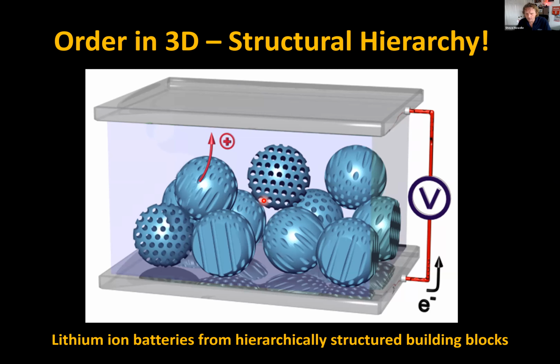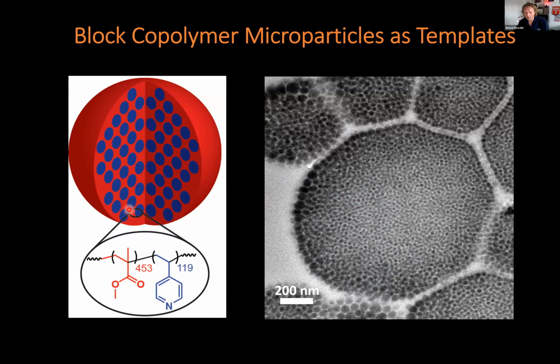So we started to try and understand if this was feasible. How do we do that? Well, first of all, we will create the microparticles, as I've just shown you, with the structure inside of them. Here you can see one of the microparticles with the structure inside. And we've chosen now to use N-vinyl pyridine, 4-vinyl pyridine, as one of the monomers with methyl methacrylate.